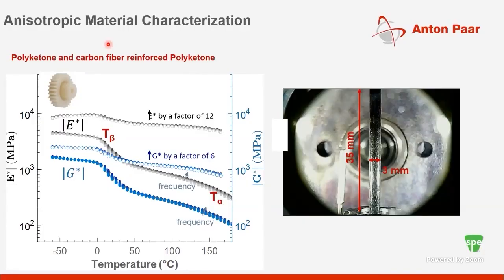Here I'm showing results using the same protocol for a polyketone and a carbon fiber reinforced polyketone. The open symbols are for the reinforced entity, and the closed symbols are for just the polymer polyketone. The fibers really result in an increase of both G star, the shear modulus measured using the rotational drive, and E star, measured with the axial drive. You can see a factor of 6 to 12 difference, and G star actually varies almost by a factor of 6.